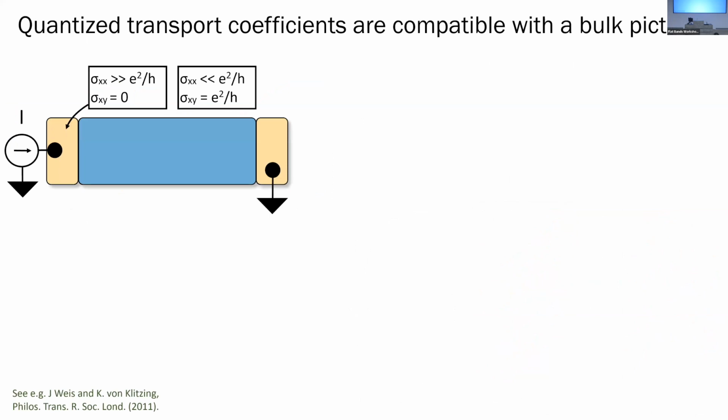Let me see. I was quite shocked at this. I really expected and wanted the current to flow along the edges. So we went back and looked in the not quite ancient quantum Hall literature, and discovered that it's actually not so clear, even in quantum Hall, whether the current truly is always confined to the edges of the sample. I'm not saying this bulk picture is what's truly going on in the samples, but I want to remind everybody about an alternative picture for how to think about transport in the quantum Hall regime that doesn't involve any edge channels.